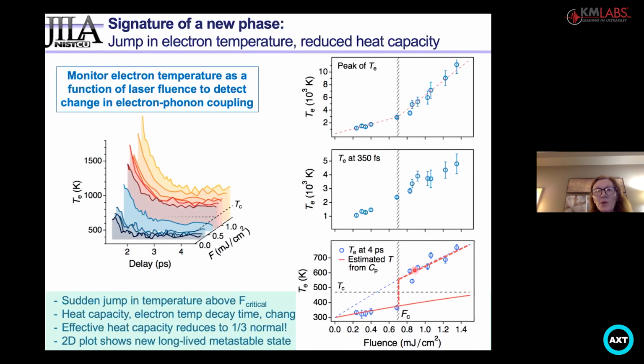Initially, the electrons are heated, but then they lose energy only to a subset of strongly coupled phonons and other strongly interacting phonons. The cross-plane phonons are not excited, and because we are exciting only a subset of phonons, the heat capacity of the material drops, and also the potential charge density wave states that we can access open up.